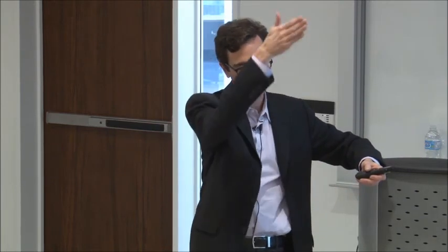So if I had the perfect structure with well phase-separated material, that might work. However, it's never been shown that that's efficient. I mean, Steve Forrest's group has some results with small molecules that aren't bad, but they're never as good as this. And that's why everyone is kind of being forced into this model where you would think the mixed stuff is bad, but it's a fact that you may have this extra driving force that the electron in here gets pushed out to the edge and it won't come back. That's the best explanation everybody has right now. Nobody knows that for sure.